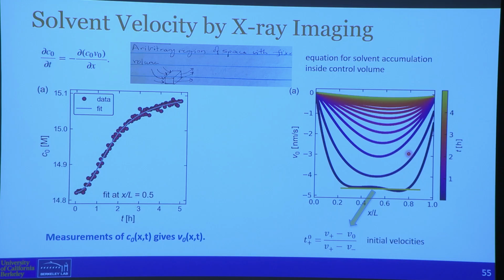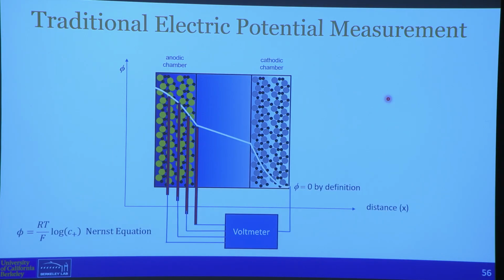Midpoint actually almost doesn't change, so it's very critical. But you can see the quality of the data and the resolution and that fit. So we get a fit from which we get the velocities. So with no adjustable parameters, we are seeing how the solvent velocity initially starts at a value dictated by the transference number and eventually goes to 0. So this is the first spatially resolved velocity profile of neutral species under electric fields as a function of space and time you've ever seen. And not rocket science.